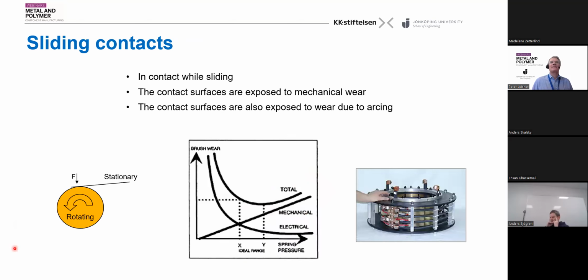So this is one type of contacts. A completely different type of contacts is sliding contacts. Here you have electric contact while you're sliding, so there is a risk of wear. The stationary part is pressed against the rotating part, and the higher the contact force is, the higher the mechanical wear will be. But on the other hand, if you try to release the contact force, there is the risk that you now and then will lose electric contact and you will have arcing. And these electric sparks will also wear the surface. And that will be a lot if you have too low contact force.